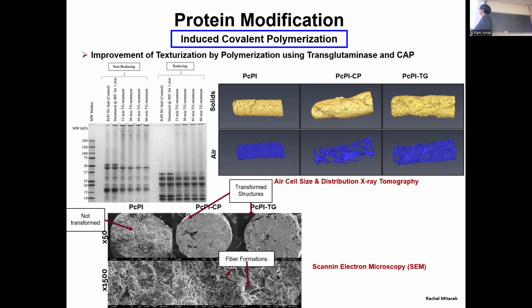So actually, the pea protein did not expand after texturization. But these treated ones expanded, and when we did SEM, scanning electron microscopy, we saw fiber formation. So we always correlate gelation to fiber formation. We want to enhance gelation through formation of soluble aggregates, and these soluble aggregates behave better for texturization.